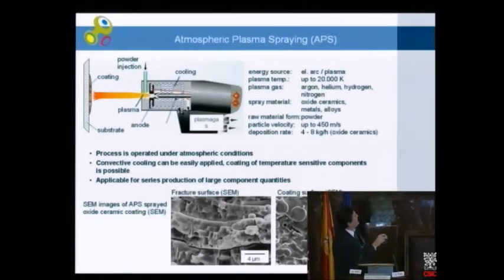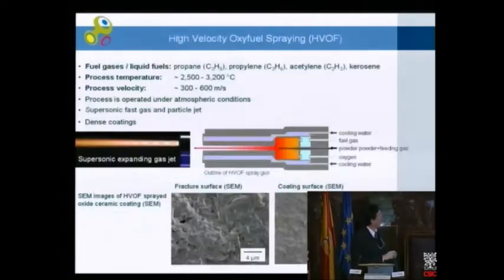In any case, we have this transition of a solid powder to a temporarily liquid, fine droplet, and the consolidation of many, many droplets to the layer, to our coating. And in the case of a plasma torch, the typical feature is this multilamellar structure, and so you can clearly tell this is a distinctly anisotropic material, mainly in its electrophysical and thermophysical properties. And that is the look from the top, so we can see the splats at the upper surface layer. So this is more or less the conventional modern plasma coating deposition of ceramics.